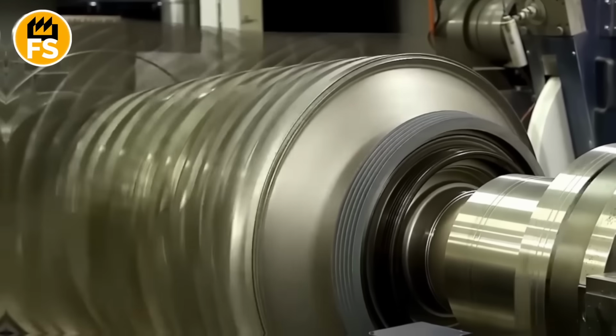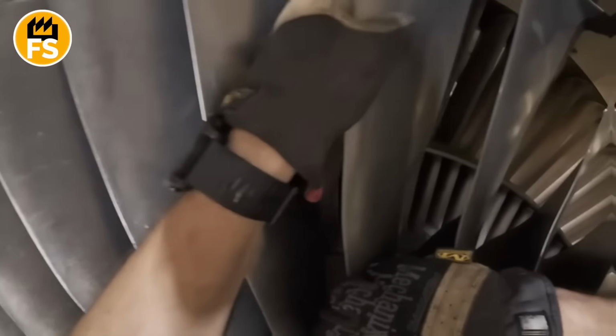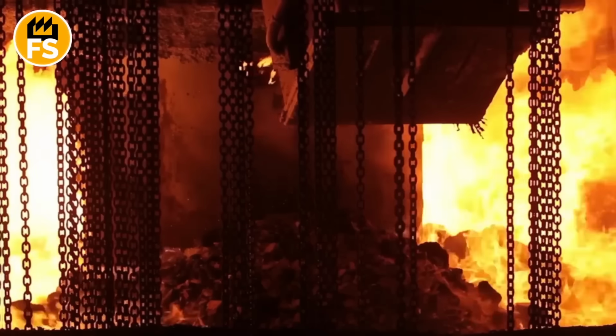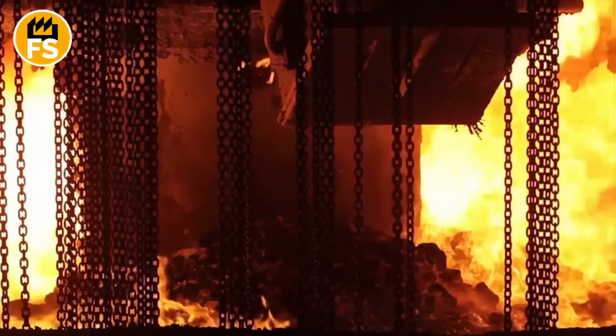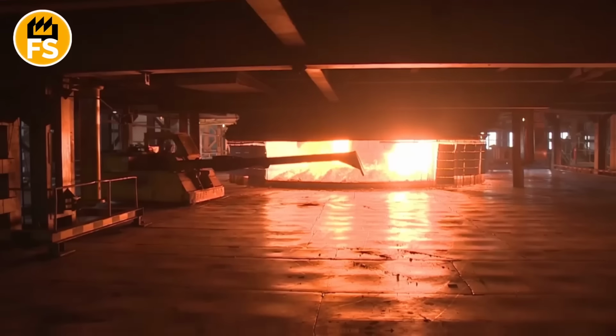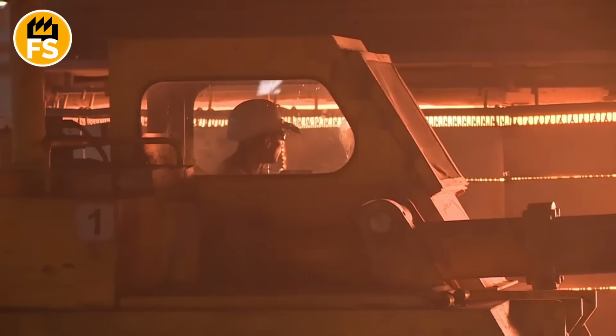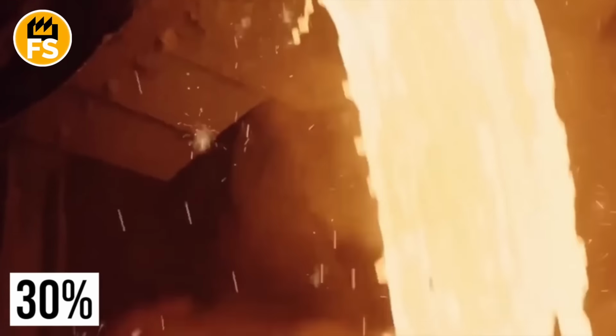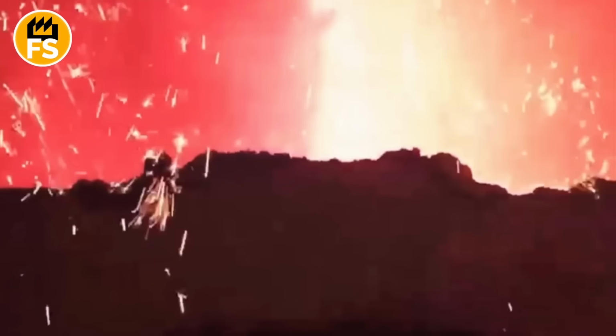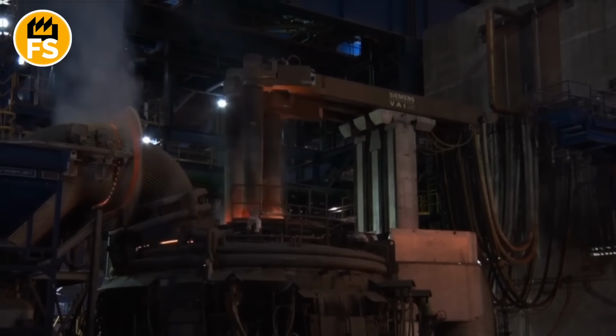Recycling rhenium from spent blades is critically important. After thousands of hours of operation, blades wear out and get replaced. Old blades aren't thrown away. They're melted down. Rhenium and other valuable metals are extracted and used again. About 30% of rhenium comes from secondary recycling. That's more than most other metals simply because of its enormous value.